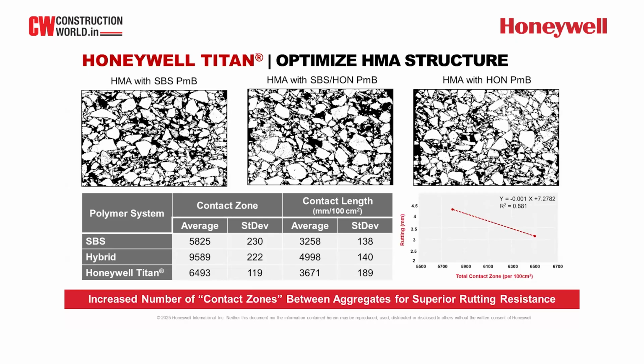And the hybrid is about 5,000, and the Honeywell Titan only is about 3,700. To the right, what we did is we plotted total contact zone number versus the rutting. So we also did a Hamburg rutting test on this core sample. Then we tried to correlate the rutting of the sample versus the total contact zone number. Actually, we have a fairly good linear relationship.